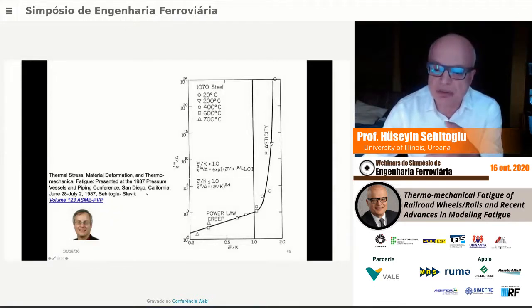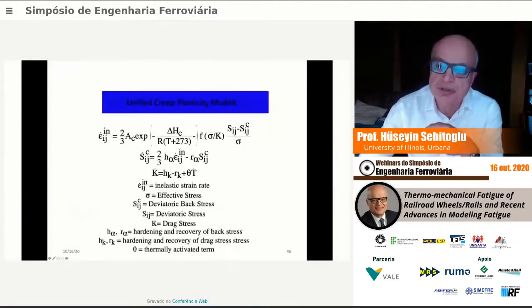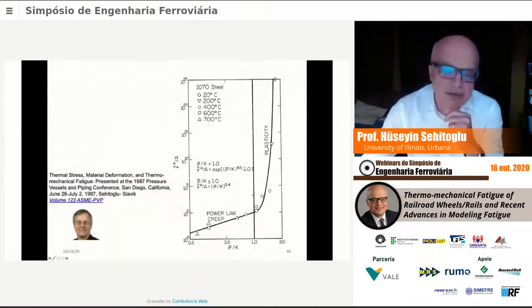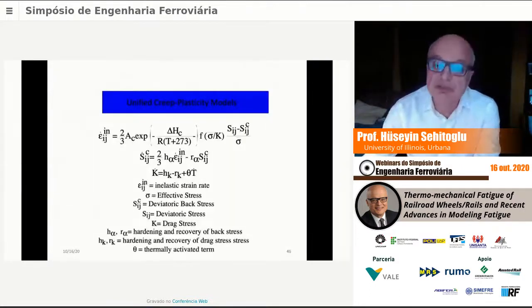This is a power law relationship. This is more an exponential relationship. And this is all the data from 20 degrees to 700. Again, all this work is done. Initial work we did was on 1070 wheel steel. Okay? And that's the description.